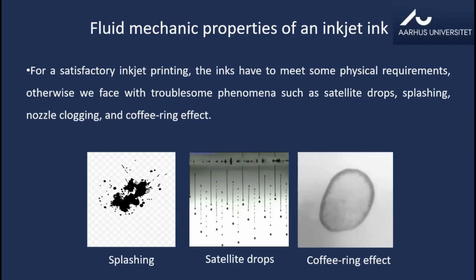The viscosity of your material, whether it's low viscous or high viscous, should be compatible with your print head. If you have a very small opening of the print head and your material is highly viscous, and you're not applying enough pressure, you will not be able to extrude it out. Conversely, if you have too big an opening of a print head and your material is low viscous, then too much material would come out and you will not be able to control it. So it's always a balance that you have to find between different parameters. Otherwise, you would have problems like splashing, satellite drops, or the coffee ring effect. Coffee ring effect is, I would say, the biggest headache for people like us.